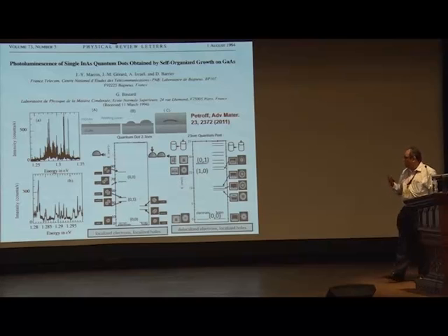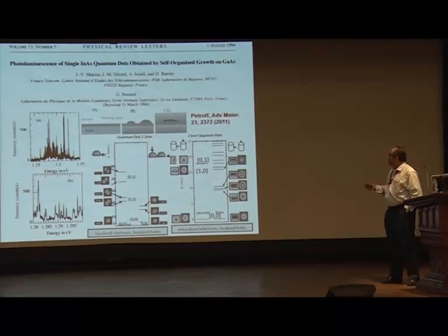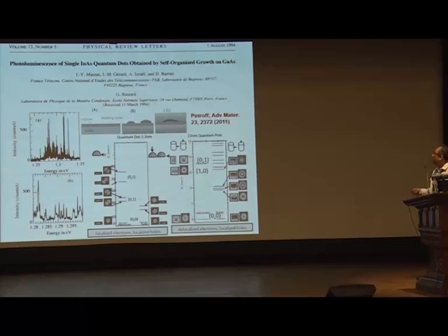One is whether the electrons are localized in the dot, whether the holes are localized in the dots, whether there is a variation of composition, whether there is a variation of shape and size of the dots. Everything will change the position of this PL. That is very well known, and so much work has been done. It is summarized in this Advanced Materials paper very well.